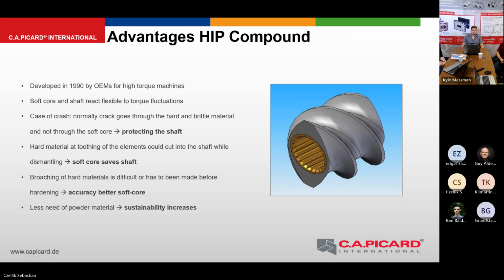Moreover, if you have a very hard element and it's through hard, you can damage your shaft by putting the elements on or getting them off because they're much harder and they could cut into the shaft. And for us in manufacturing, we could have a much better accuracy because we can do the broaching after the hardening. If we have a through-hardened element, it's normally not possible to do the broaching afterwards. And one environmental aspect, if we have a soft core, we don't need that much of this powder, which is very expensive and where a lot of energy is put in.